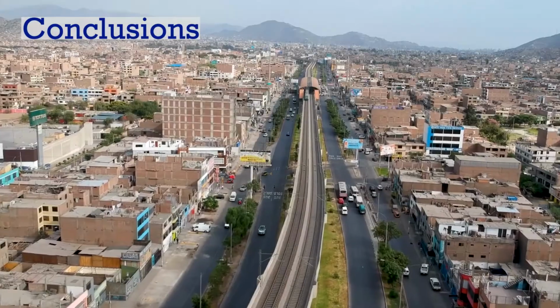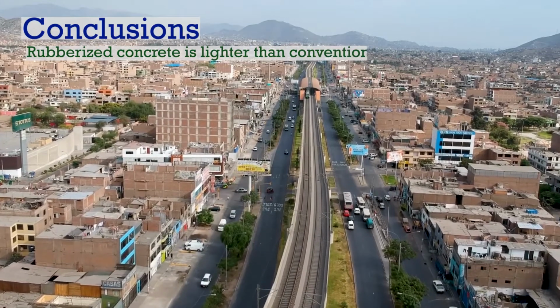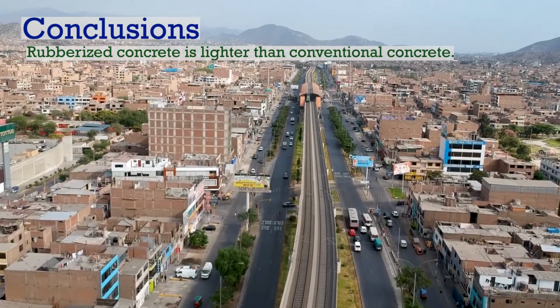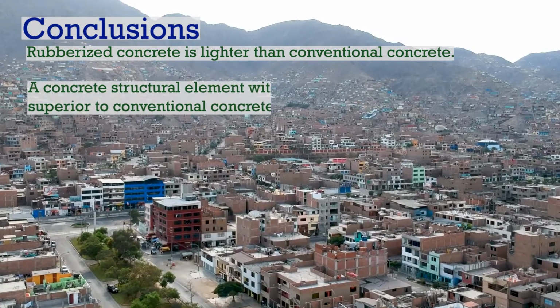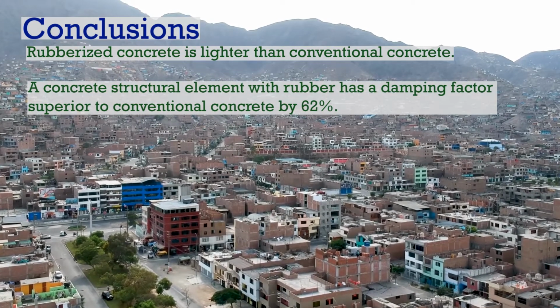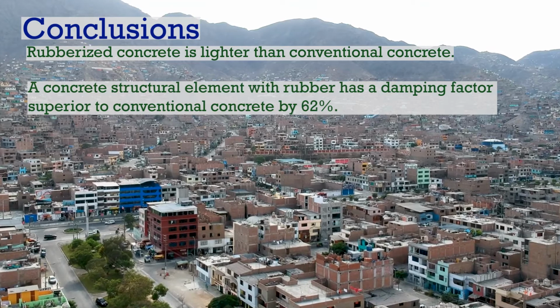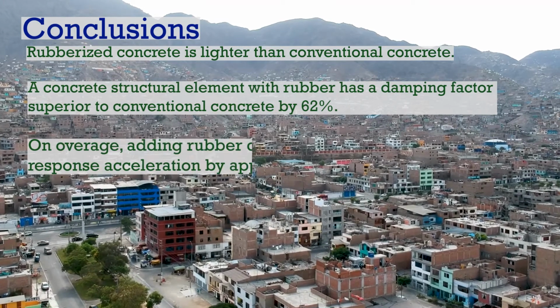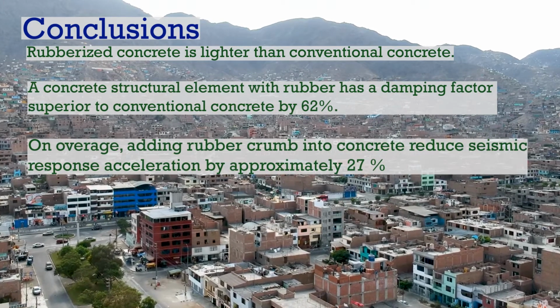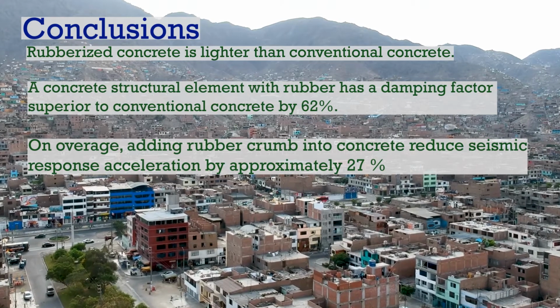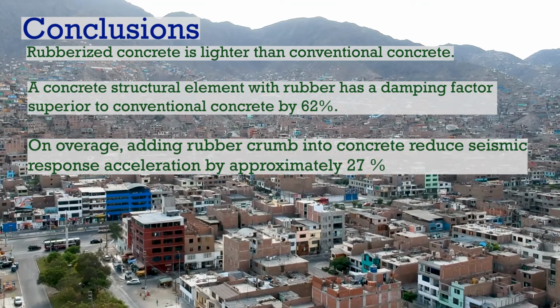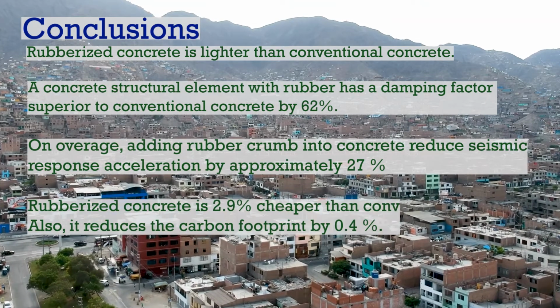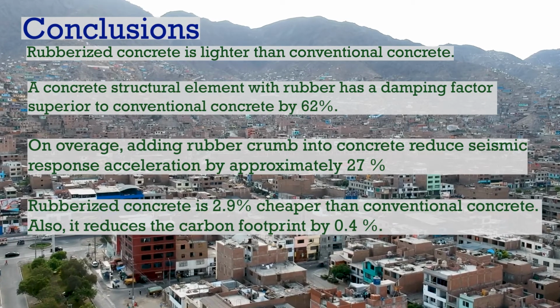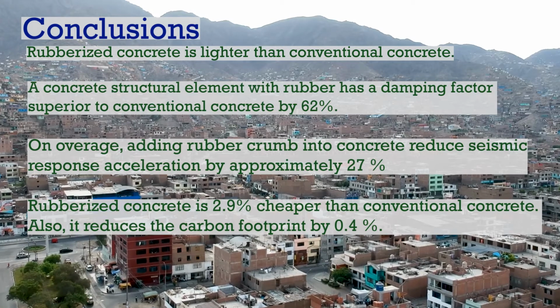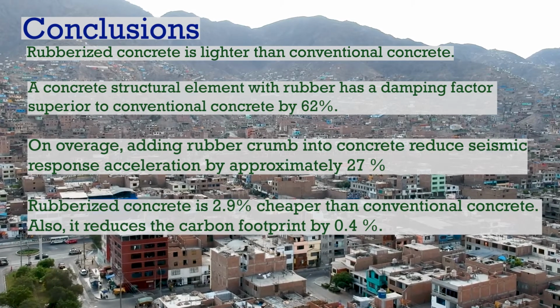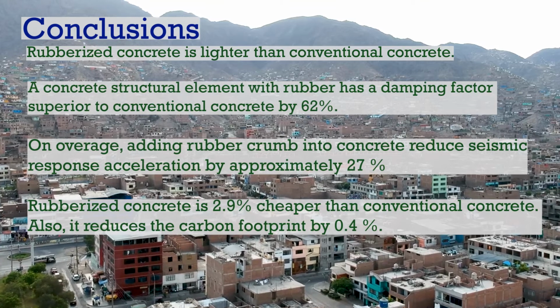Conclusions. First, rubberized concrete is lighter than conventional concrete. Second, a concrete structural element with rubber has a damping factor superior to conventional concrete by 62%. Third, on average, adding rubber crumb into concrete reduces seismic response acceleration by approximately 27%. Finally, rubberized concrete is 2.9% cheaper than conventional concrete. Furthermore, it reduces the carbon footprint by 0.4%.